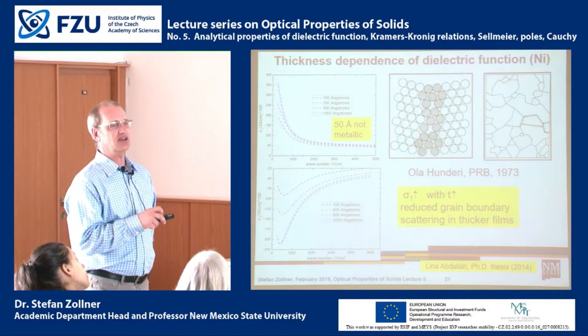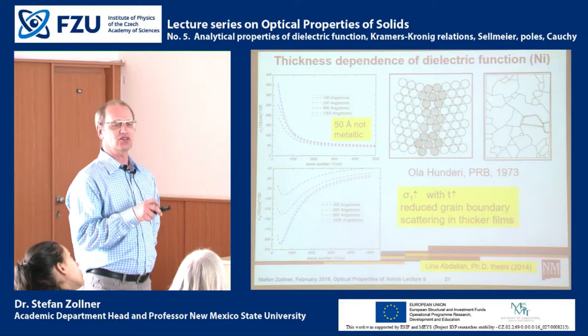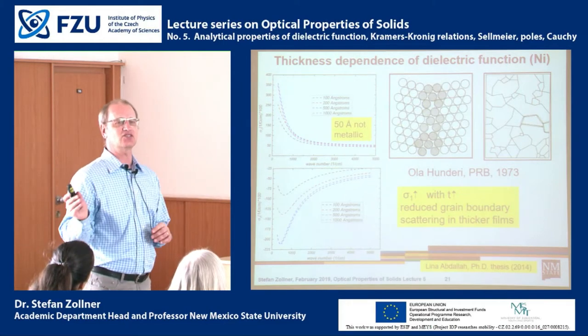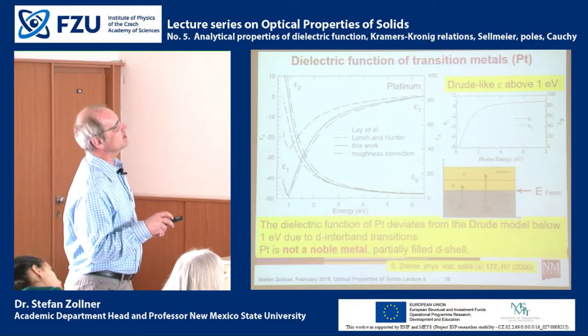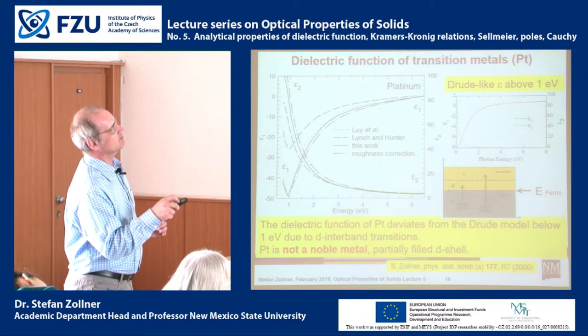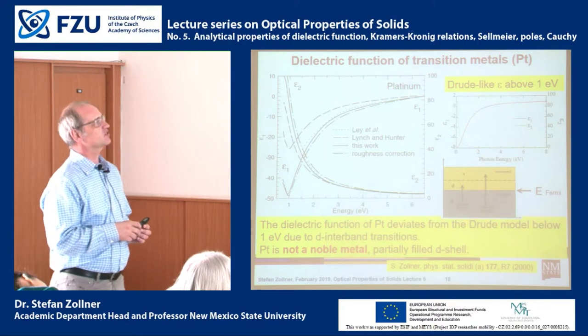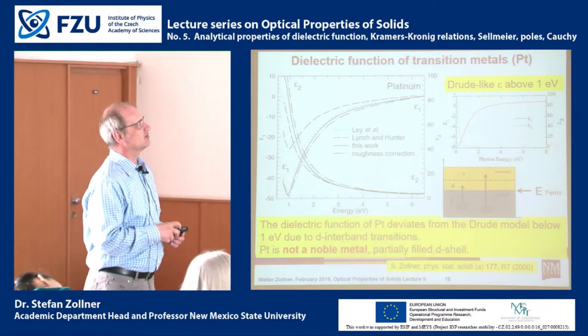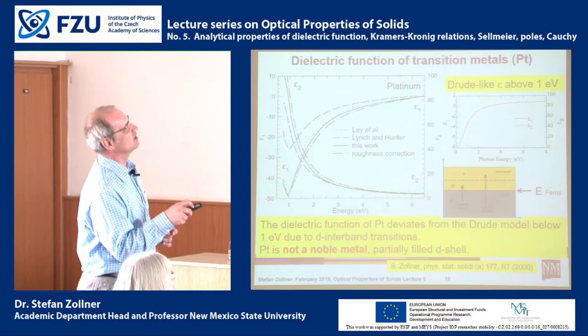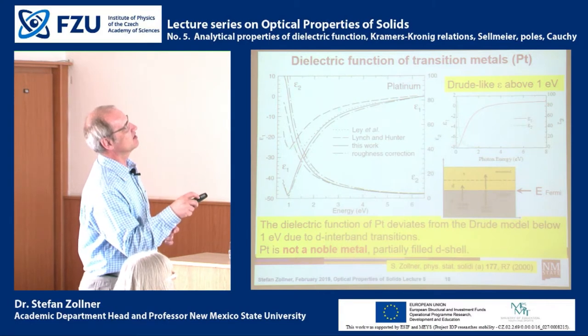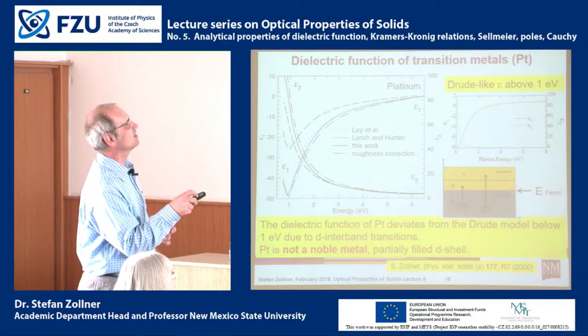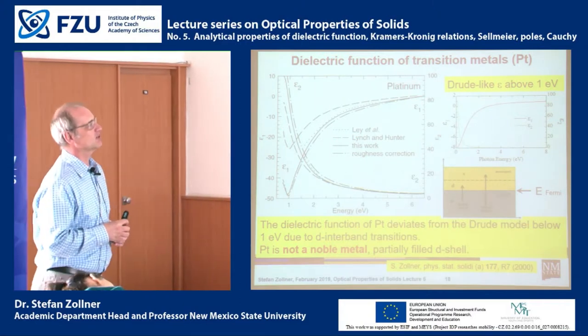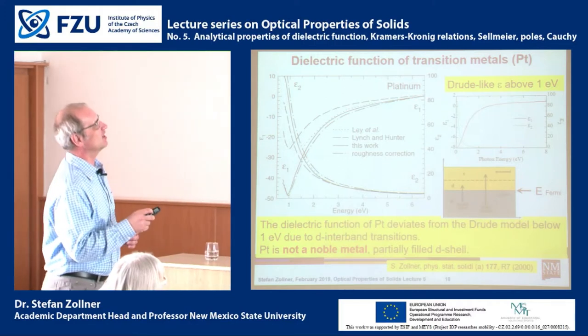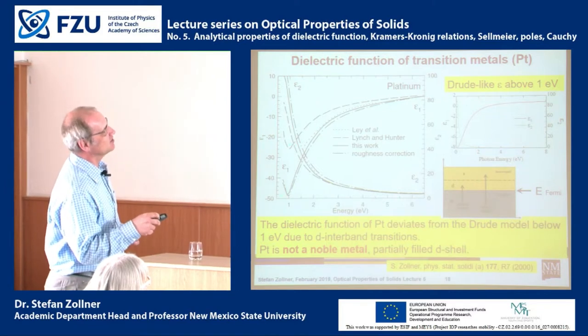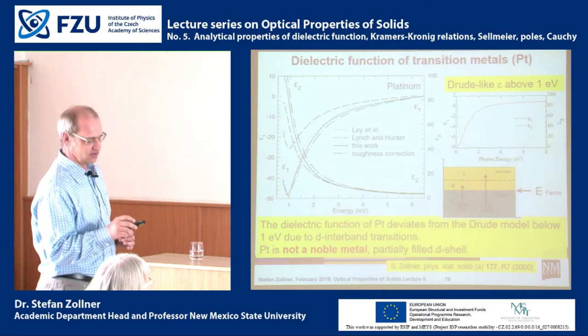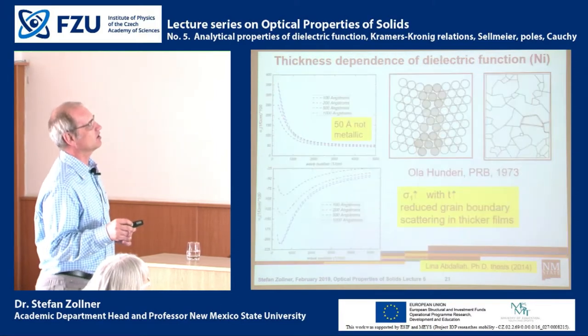If you look at silicon, everybody agrees on what the dielectric function is. It may depend on the surface, but there's not much debate. Nobody says, oh, this is my silicon and this is your silicon. They're all the same. But when you look at metals, you see here these are different measurement results for platinum, and there are very significant differences. And it's not just that you need to make a roughness correction. The dashed line here is the result of Lynch and Hunter, and I knew Dave Lynch very well when I was in Iowa, so he's a very diligent person. So this is not just that he was careless, and then these were our ellipsometry measurements later. So there are significant differences in the metals based on their microstructure and other properties.